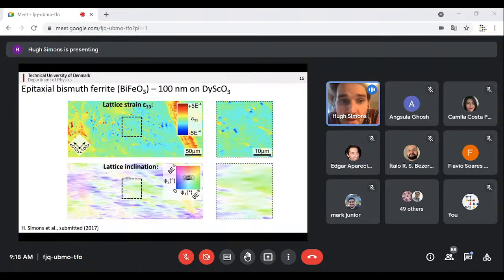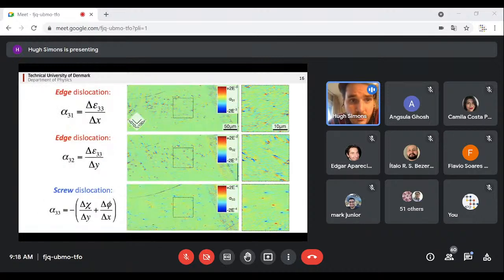And actually, what we saw were these changes in strain and these changes in misorientation. And although we were looking for dislocations, it wasn't so obvious to me how or why these were dislocations. But I got talking to some of the people that work in solid mechanics in our university, and they gave some advice about how to analyze these in terms of the dislocation density tensor. And it turns out that when you measure misorientation changes across certain directions and also different strain components, you can actually isolate very specific components of this dislocation density tensor. And because of the particular HKL we chose when visualizing these samples, these actually corresponded to very relevant coefficients.